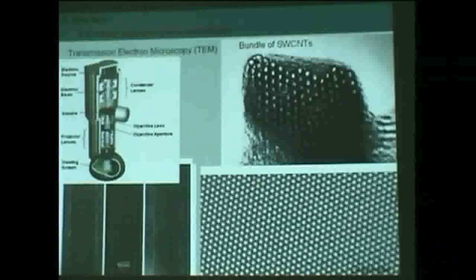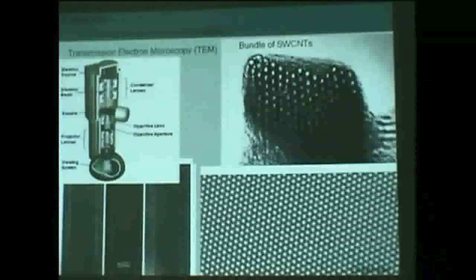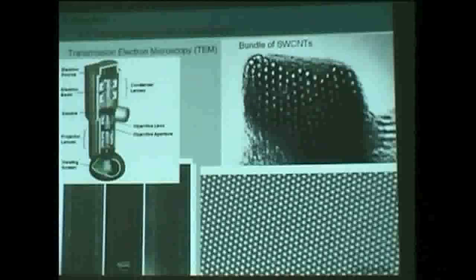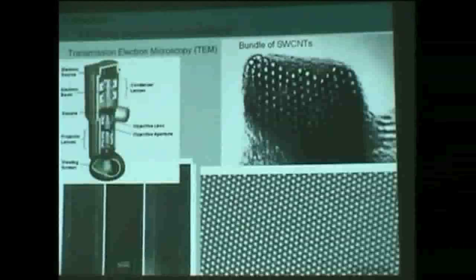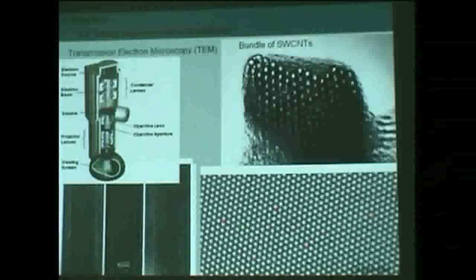You also have some contrast related to the carbon-carbon bond, because you have some electrons. Actually this technique is not sensitive to neutrons - it's very sensitive to the presence of electrons. So here it's like a map of the electron density in this plane. TEM is very sensitive to the electron density locally, and this is why it makes this hexagonal network.